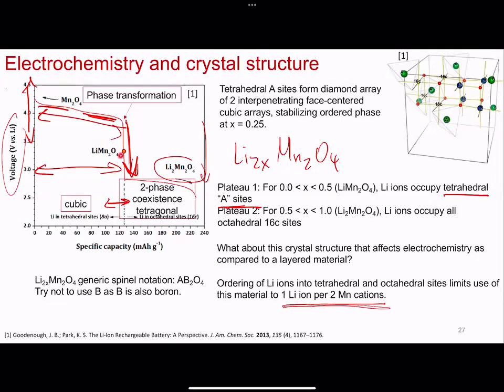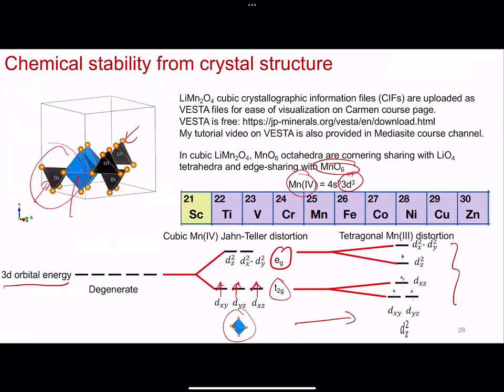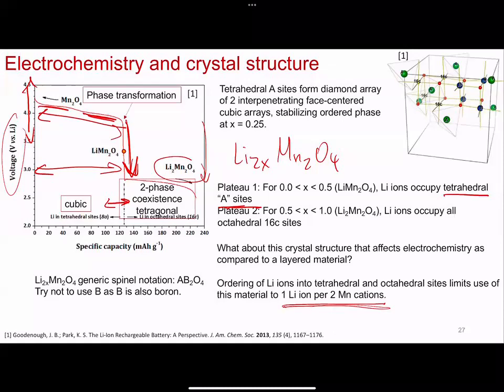In this particular system, lithium manganese oxide, there can be a two-phase coexistence between the cubic phase and the tetragonal phase, and manganese dissolution is an issue because of the instability of manganese 3+ in the tetragonal crystal structure. So it's the phase transformation itself that really limits the use of this material, if you wanted to stop this phase transformation and not experience volumetric changes, which would be deleterious to your electrode once you fabricated it, right? Once you made the composite.